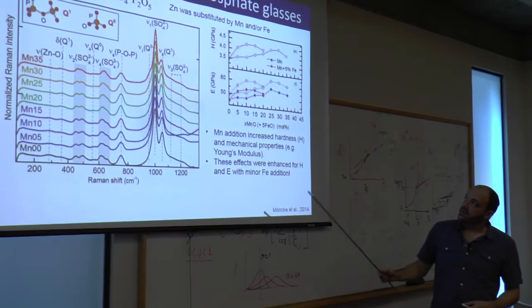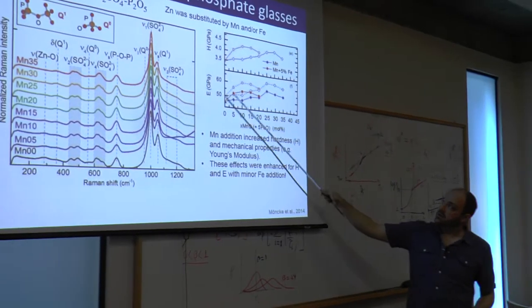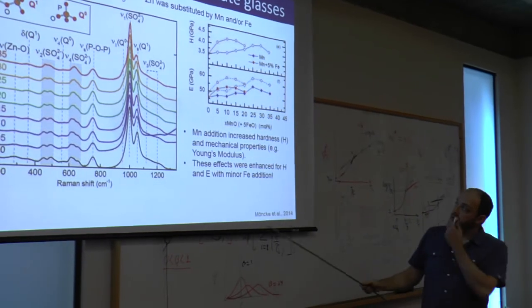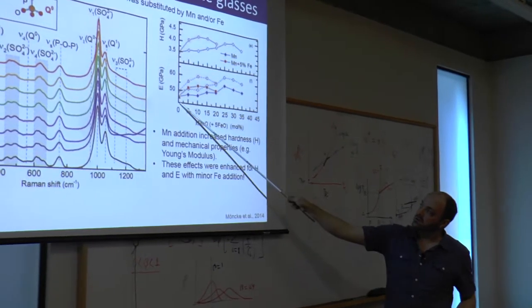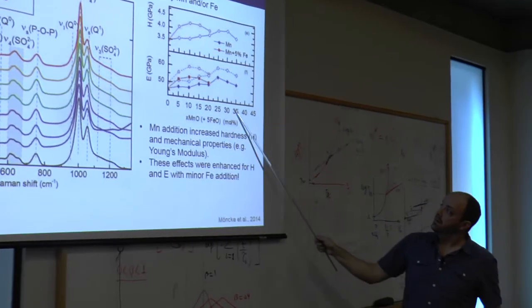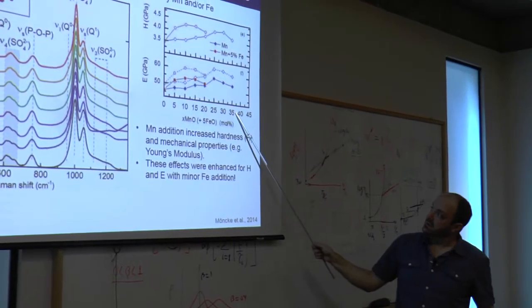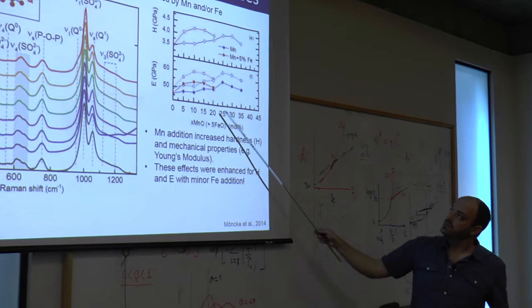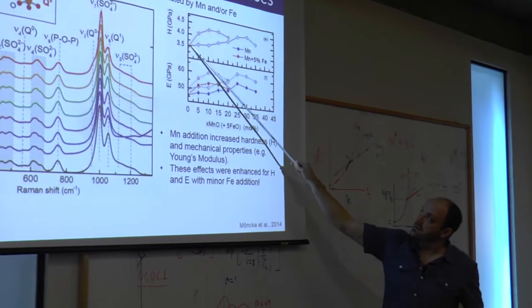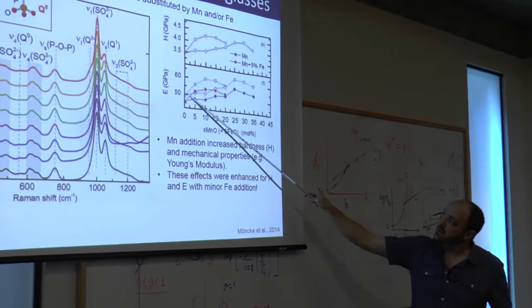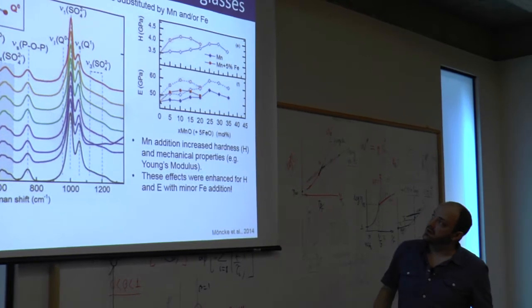What they saw when they looked at the properties is actually the hardness and Young's modulus. As you add significant amounts of manganese, not magnesium, you increase the hardness by 50% and you increase the Young's modulus by about 10 GPa.